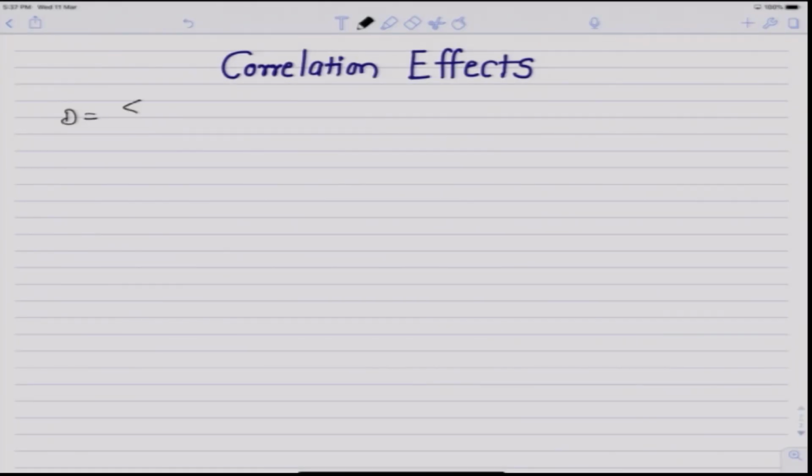Just a recap over last couple of lectures, we derived the expression for diffusivity in terms of mean square displacement as D equal to average of x square over 2 tau, where x square inside the triangular bracket denotes the average of square of x projections of net displacements of all the atoms, and tau is the small time interval.